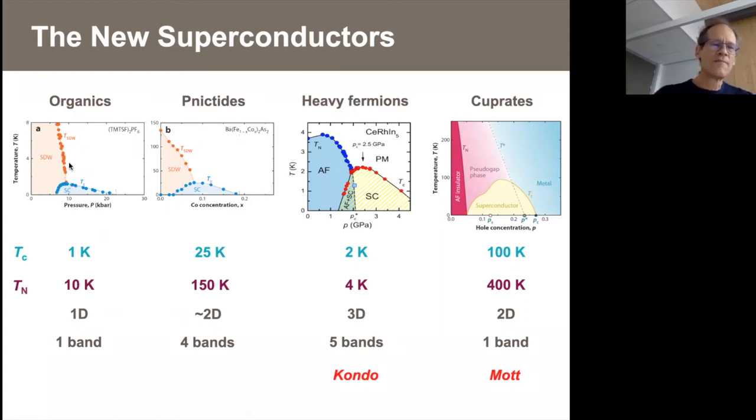This is true in the organics, where Tc might be 1 Kelvin, or the iron-based superconductors, where Tc can be as high as 50 Kelvin. It's also true in the heavy fermions, where Tcs are slightly lower. And this raises the question of whether cuprates should be thought of as another reflection of the same type of phenomenon. But it's certainly not immediately obvious, because the real phase of long-range antiferromagnetic order ends here before superconductivity